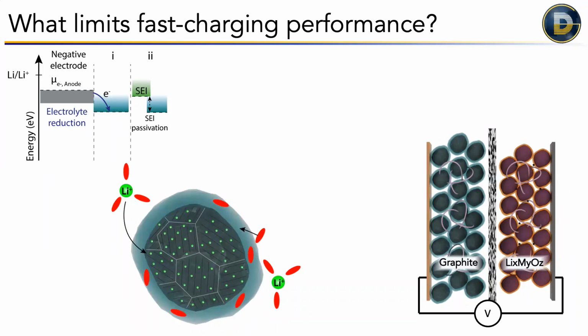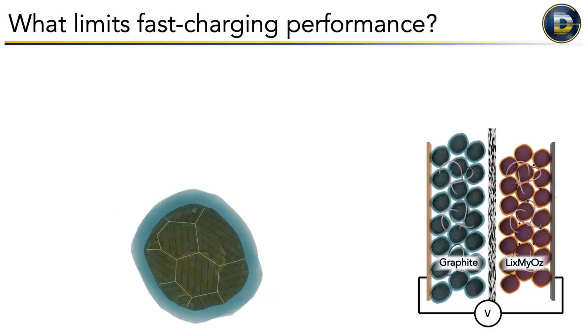If this didn't happen, if this didn't form a passivating shell that protected the graphite from further reaction, you wouldn't even be able to discharge the battery once, let alone 10,000 times. But so then we're left with this structure, the graphite in the middle, and then this, what we call SEI, which is a solid electrolyte interphase on the outside. This is the magic that makes a lithium-ion battery work. And it was a serendipitous discovery. It wasn't designed this way, it just worked, which is really remarkable.